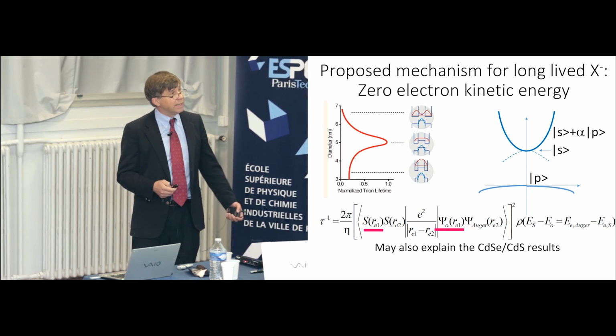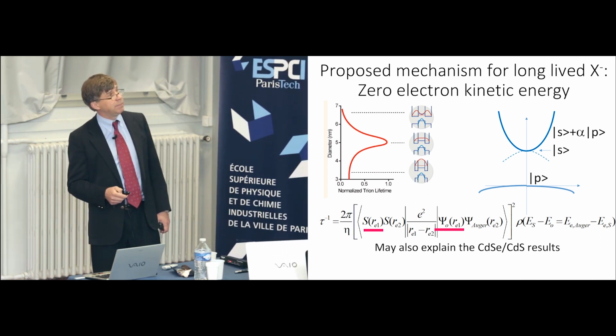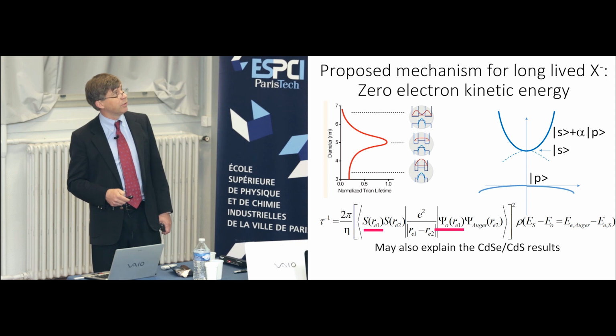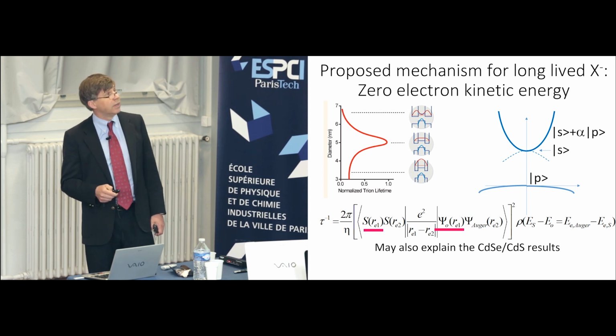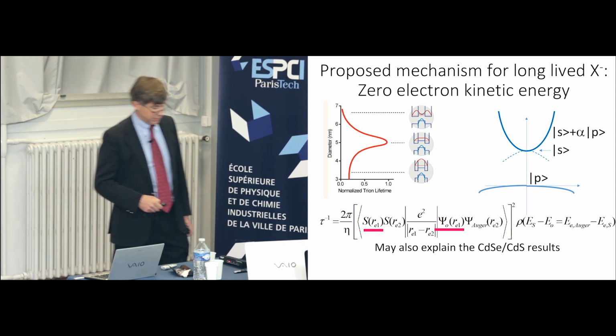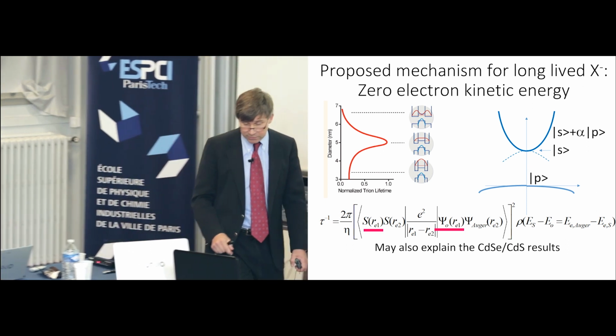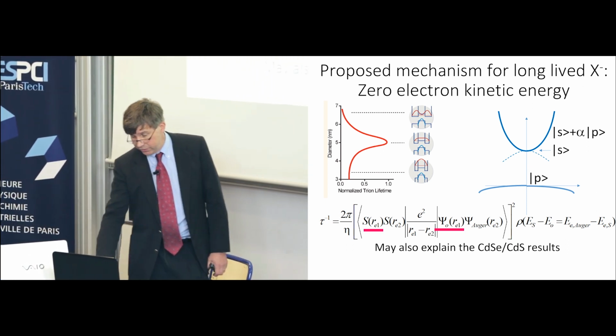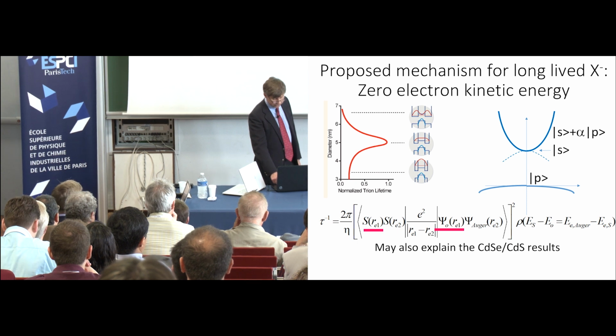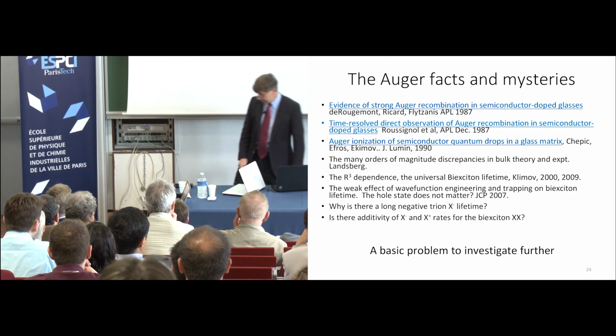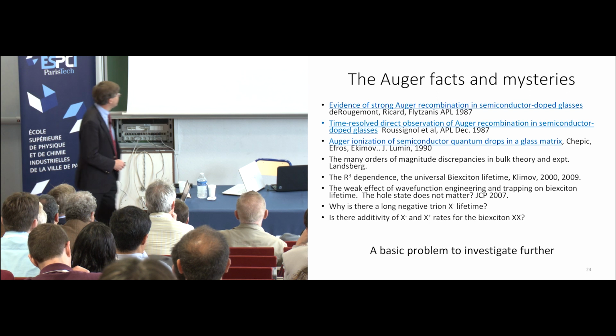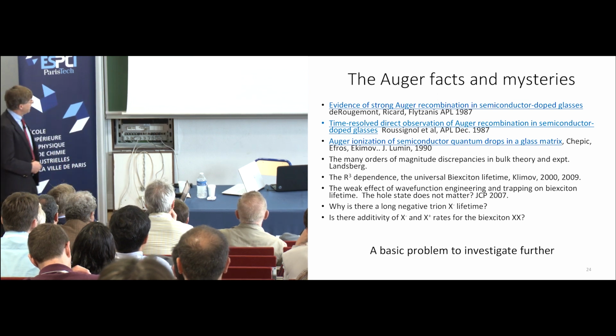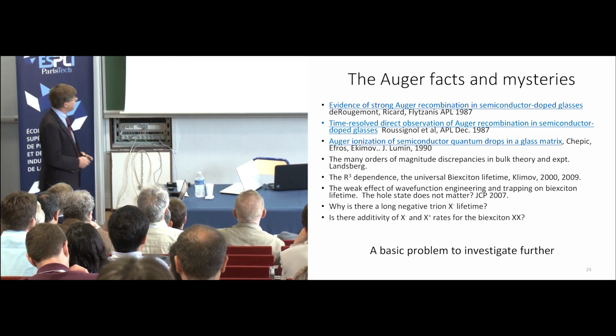And so the idea was that as the spatial overlap is big, then the coupling becomes stronger and the trion lifetime becomes shorter. And so really there's this optimum point here where the trion lifetime should be the shortest. So that's a proposition. I haven't heard yet from theorists, published of course. I haven't heard yet from theorists whether it's crazy or not. But that's where we are in our search for understanding further the Auger and making bright dots.